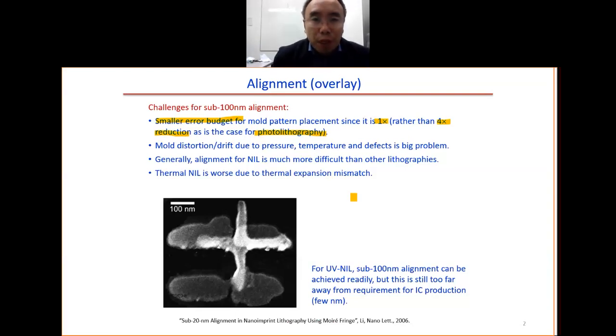The big problem for the imprint is the mold distortion and the drift because you need a high pressure. When you have high pressure, it's very hard to keep it stable, there may be some drift, and this will damage the alignment. And also the temperature. Then you have the thermal expansion mismatch. For the thermal imprint, it's very difficult because of the thermal expansion mismatch. For the UV imprint, it is easier, but still very difficult because of the high pressure.